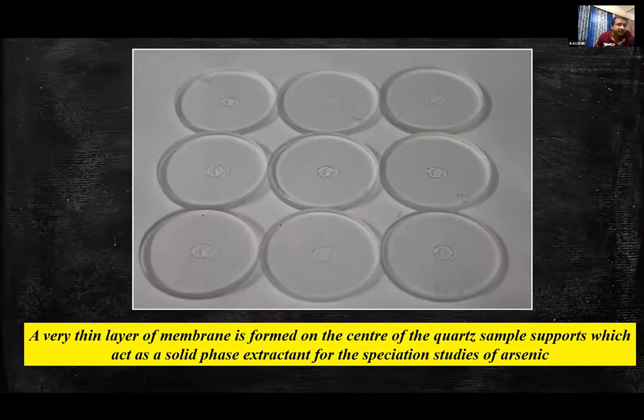As you can see, after immobilization of the NMDG, the quartz sample supports look like this. A very thin film or membrane has been formed and the TXRF condition is retained. This NMDG membrane basically acts as a solid phase extractant for the speciation studies using the pre-concentration method.